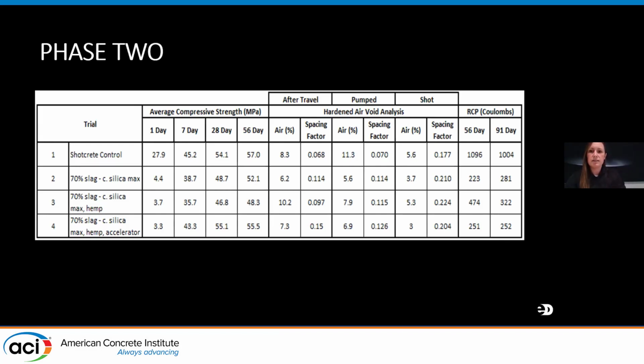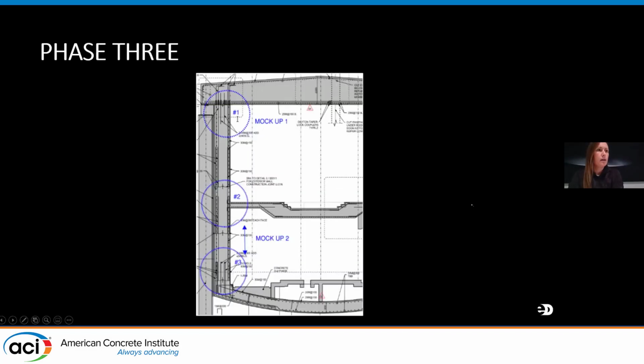To be classified as a class C1 mix, the rapid RCP value in 91 days has to be less than 1,500, where you can see all of these are way lower, the maximum being 322. And then we also did shrinkage testing, and a low shrink mix is 0.04% each. I think the maximum for this was 0.032. So very good results.